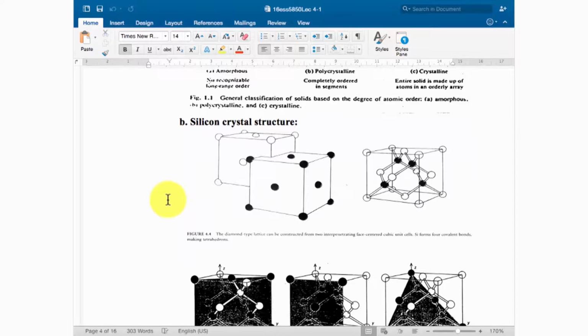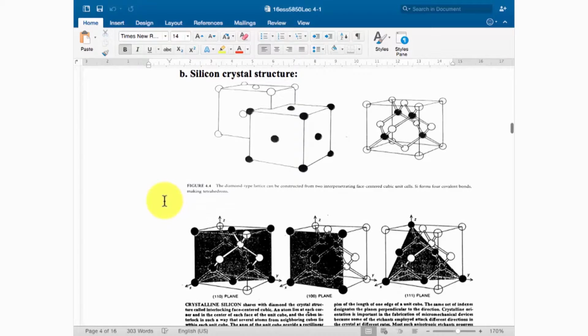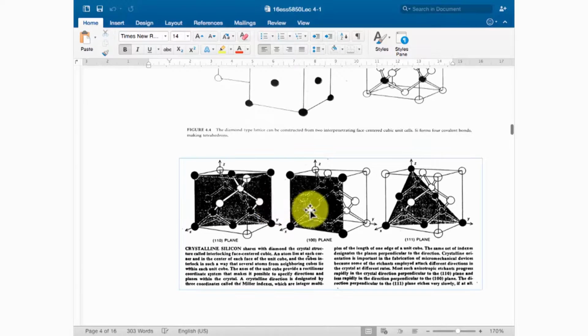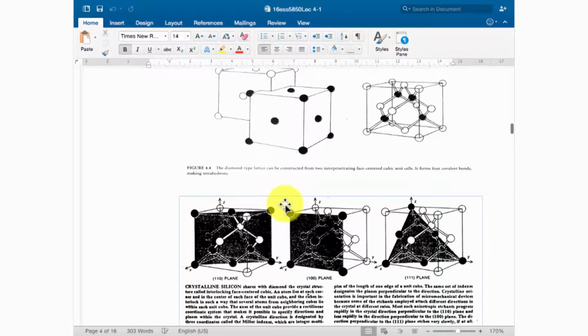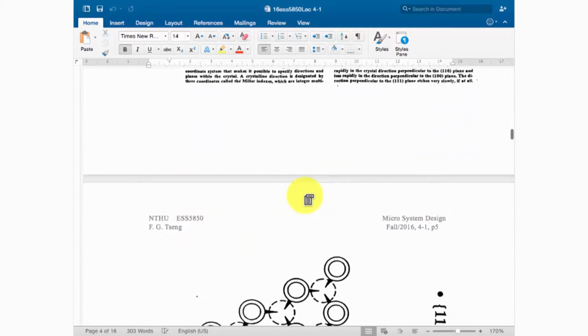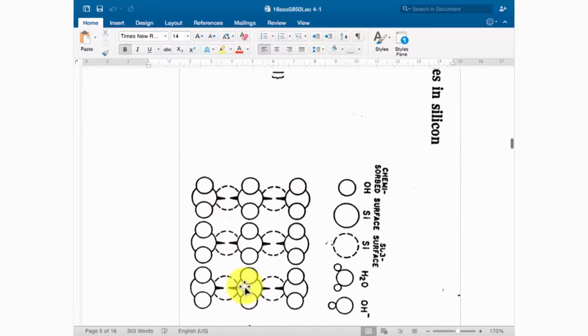So in this kind of single crystal silicon, we'll consider three important planes. Actually, there are many different planes. We especially consider three important planes, because in the next step, we will introduce different etching rates on these three specific planes. So that's why we mention the direction and also orientation, okay. So the first one we call the 100 plane. For the 100 plane, when you look into the atomic structure, you can see they form rectangle structures, very uniformly distributed and aligned to each other. Okay, that's when you look into the 100 planes.